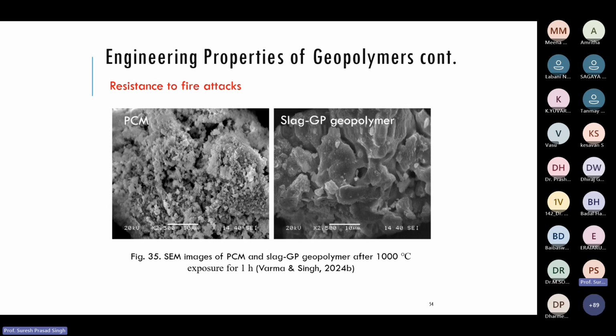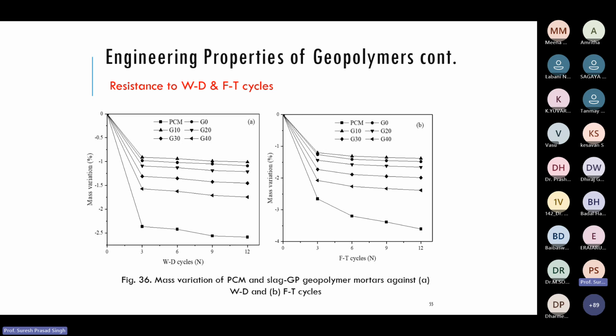So these are the structures retained. This told that this geopolymer is very good in resisting high temperature exposures. Then again, a similar thing, the wetting, drying, and freezing-thawing cycles. This is the number of cycles. It is exposed to a total of 12 cycles of wetting, drying, and freezing-thawing. And after 3 cycles, 6 cycles, 9, and 12 cycles of exposure, we determined the mass loss, and the residual strength also we have measured.